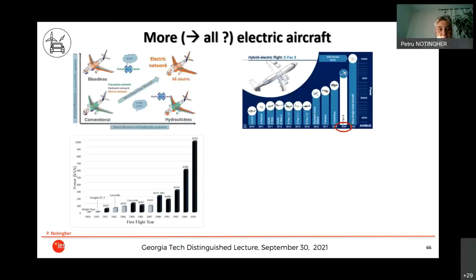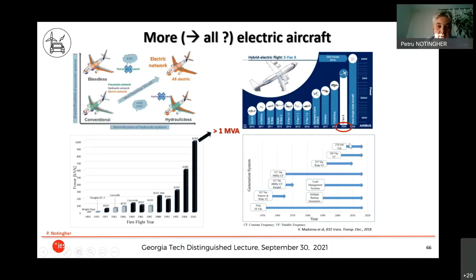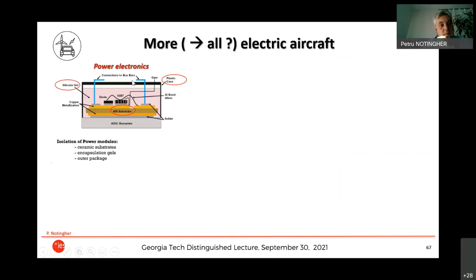So we have increased a lot the power in the airplanes. We are now at more than 1 megawatt for the B787. And if we want a hybrid airplane, we will go up to 10 megawatts and even to 20 megawatts. And this means that the onboard networks will have to be above 800 volts or even 3 kilovolts, and today we are only at 270. So there is a huge increase in these values, and this will translate in the increase of the temperature. Because if you want to do this, you must use power electronics with SiC dies, and you will need insulators which will be able to withstand all this temperature and also the increasing field, because you want to make them more compact.